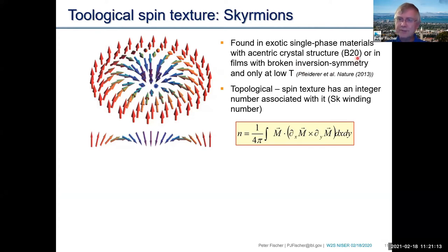They had inversion symmetry broken, but that only happened at very low temperatures. Now, in the meantime, our community has demonstrated that you can also generate those kinds of skyrmion textures in multilayered films where you have interfacial Dzyaloshinskii-Moriya interaction.